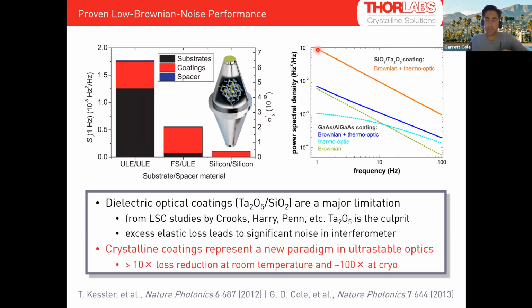Crystalline coatings show a significant reduction, and this was after something LIGO and some of these groups have been looking into for a couple decades. So that was a very exciting advancement. 10 times elastic loss reduction at room temperature and up to 100x at cryogenic temperatures.